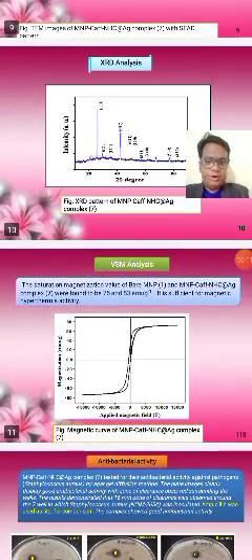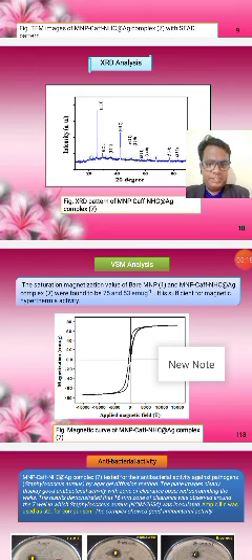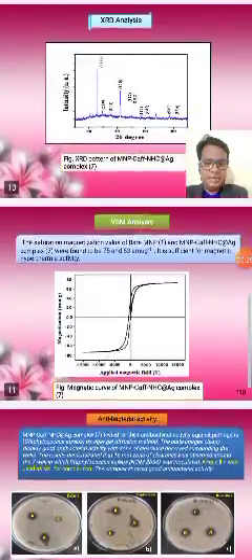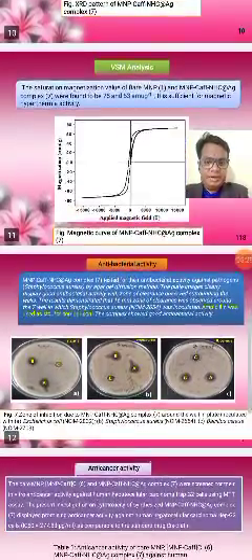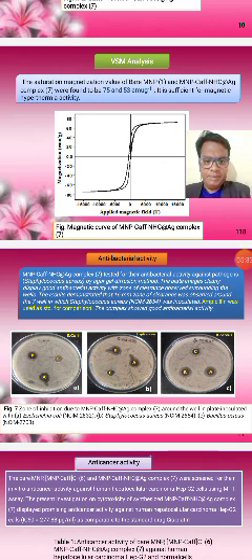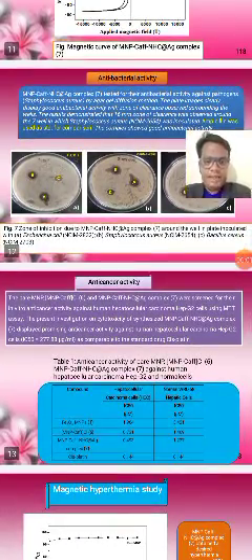Further XRD analysis of the product indicated that the Fe3O4 nanocore is well preserved during the multiple functionalization, and the product has good purity and crystallinity. These are the different peaks, and they match the standard JCPDS card. Then we checked the magnetic character. As we are going to evaluate it for magnetic hyperthermia, we checked its magnetic properties using a vibrating sample magnetometer. These VSM curves show that the complex has a magnetic moment of 53 EMU per gram, which is less than the bare MNP at 75 EMU per gram, but sufficient for the magnetic hyperthermia experiments.